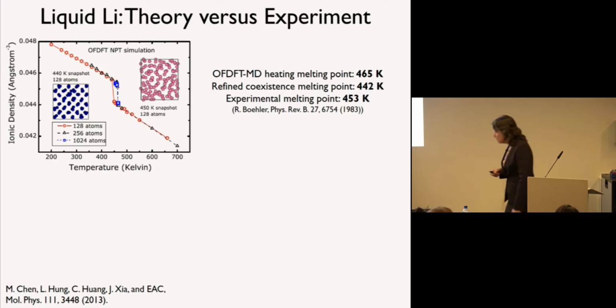Anyway, I'm going to now move to some results and show you how well you can do in describing the solid-liquid phase transformation in liquid lithium. The melting point that's been measured experimentally is 450 degrees Kelvin. This is just one example. We've done rigorous coexistence simulations between solids and liquids. If you do a simulation that heats the solid and looks for a discontinuity in the ion density as a function of temperature, you can also get an estimate of the melting point, shown here. These are two different ways to do the simulations, and they bracket the experiment.